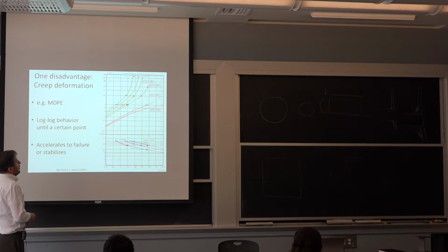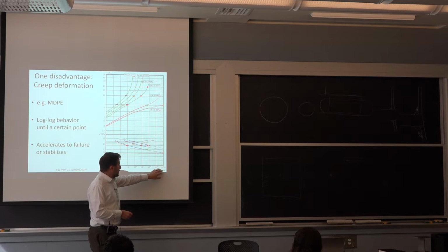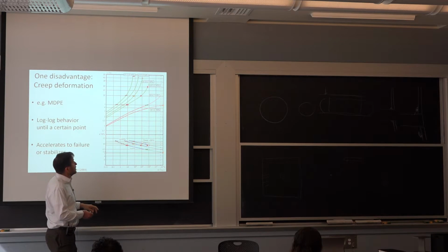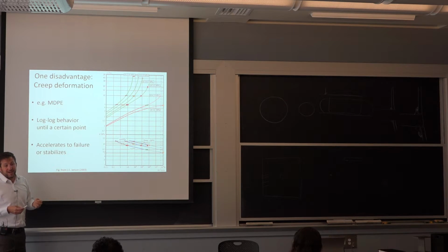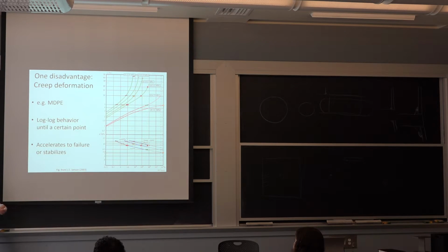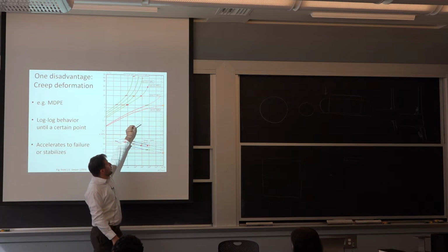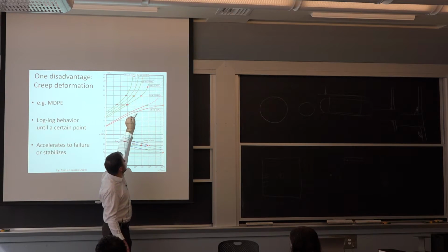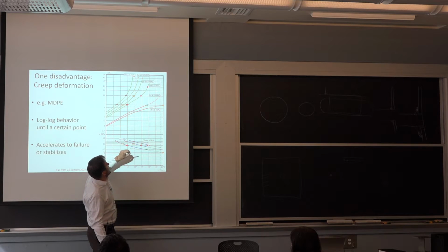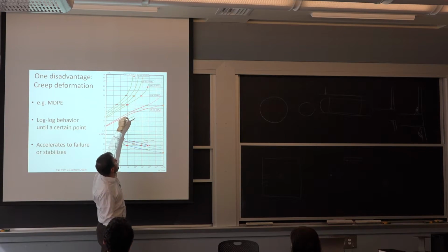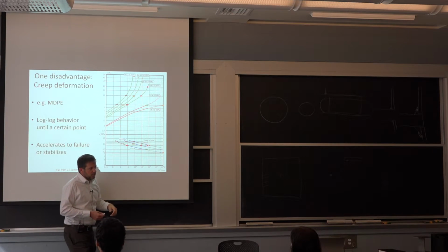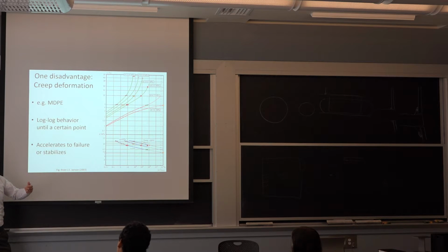So the problem is if I keep going and I'm looking at a pipeline that needs to be designed, say, a 50-year life, eventually I can literally break in a very sudden way. So there are two things that happen as the plastic deforms. One, it becomes longer. That's just the flow. But there are also these microvoids that will form in it and can lead to these more brittle fractures. So the brittle fracture happened here at a lower stress level. And when you were at a higher stress level, the green curve, so 10 plus megapascal, you're soft enough that you keep deforming and deforming. So you're almost forming it into something else without breaking it.